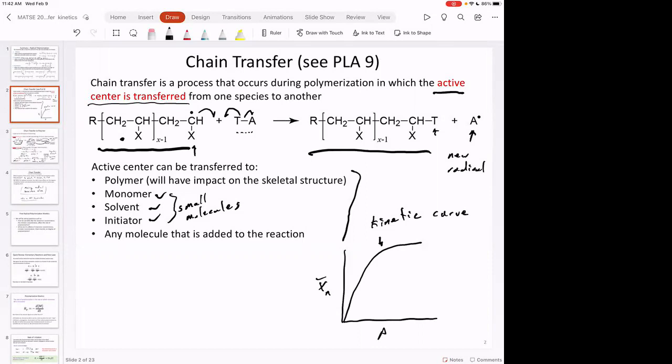Or in this case, we've drawn a chemical reaction where T, which is any sort of fragment of this molecule, could be a hydrogen, quenches that radical based on pushing these half arrows. And then because you take this covalent bond between T and A, and one electron goes one way, one electron goes on to A, that automatically puts the radical on A because it's an unpaired electron.